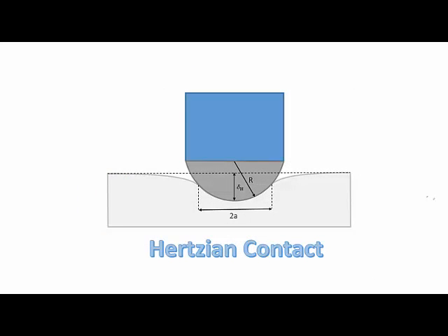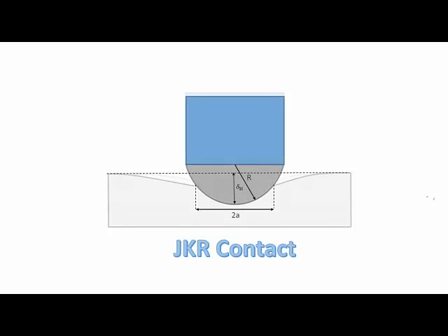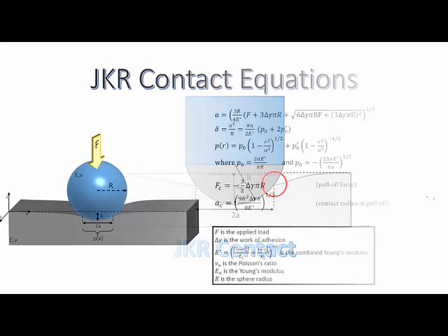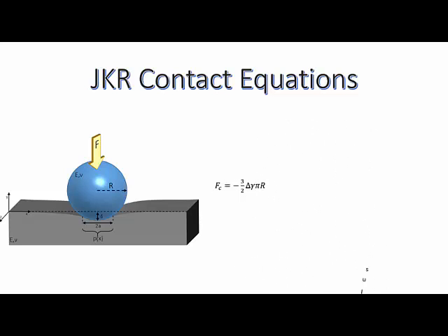First, the intuitive. The adhesive interactions increase the depth and contact radius of the contact. We also see a neck at the edges of the contact shape that looks almost like a solid meniscus. Finally, the non-intuitive. Because of the spherical shape of the contact, the elastic properties cancel out and do not affect the tensile load sustained before separation, also known as pull-off force.